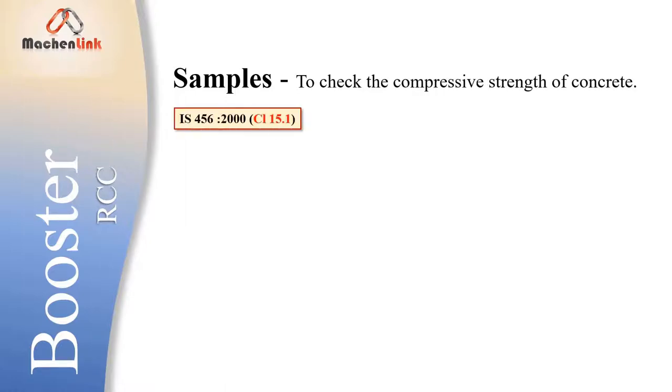Let me explain you Ayush. First, we take samples from fresh concrete to check the compressive strength of concrete. Because according to IS 456, if you look at clause number 15.1, 28 days compressive strength shall alone be the criteria for acceptance and rejection of concrete.